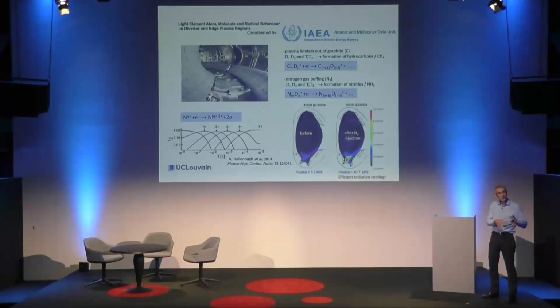So this machine that was studying multiply charged ions could be used to study the destruction and evolution of carbon-containing molecules. That would be, for instance, methane with deuterated methane that would get ionized and dissociated. And the same type of chemistry, because we could call that plasma chemistry, would come when you introduce nitrogen on purpose to cool the plasma in front of the divertor. That's what is on the bottom here. It doesn't work, that doesn't matter. So you could introduce nitrogen on purpose and hope, and this has been demonstrated to work, that destruction of this molecular nitrogen and in the end, multiple ionization of the nitrogen atom would produce the radiation that you need. So this is one kind of studies we perform.